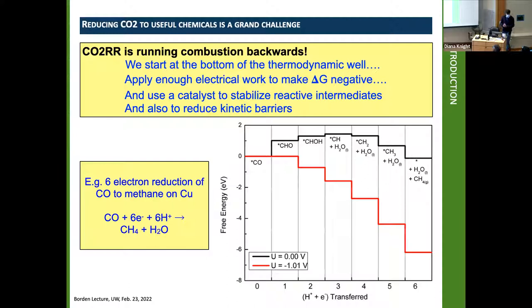This is a cartoon of the free energy landscape associated with the 6-electron reduction of CO to methane, which is the end of the 8-electron reduction of CO2 to methane. Basically, the red descending staircase is what happens when you do electrochemistry with about 1 volt of bias. From a thermodynamic point of view, all of the relevant intermediates, surface-bound CHO, surface-bound CHOH, surface-bound CH, CH2, CH3, and finally methane, are all thermodynamically downhill as we do the 1 volt of electrical work associated with each electron transferred. And of course, that's the idea.